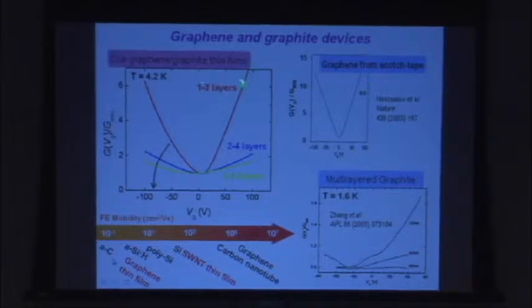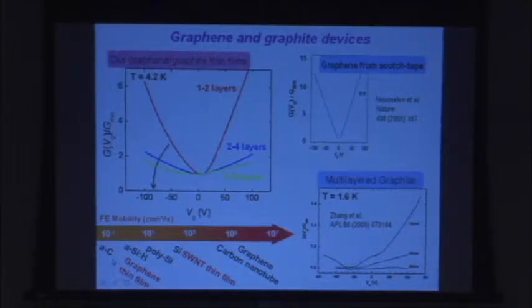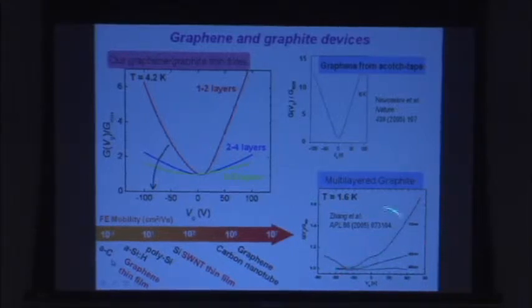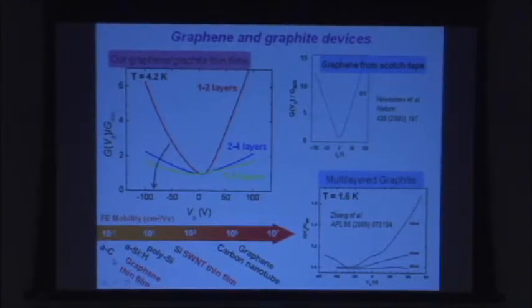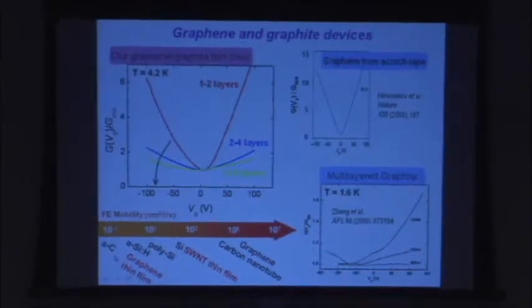If you have just a few layers, you have really a characteristic like an individual graphene flake. The more layers you pile up, the more the characteristic gets flat. That is basically what's going on when you have graphite. This is what people got when they were trying to use graphite. The only caveat, the only point to be reminded, is that this patchwork doesn't have the mobility of the individual graphene flake, because of course there are junctions.